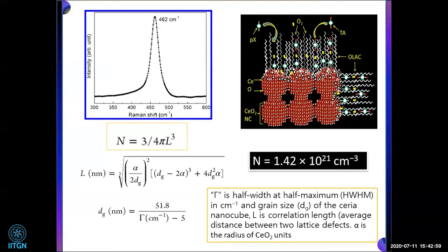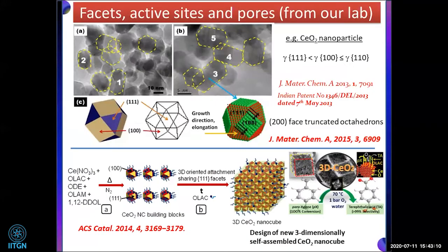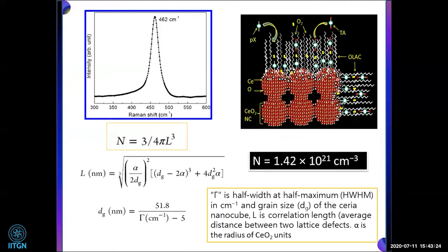So what is that? It is actually when we prepare the nanocrystal, it is engineering, right? We are doing crystal engineering. With the help of this, as I said, using surface selective solvents or surfactants, we can make the nanoparticle with special, exposed facets. So we made that, and we got only 100 facets, and that gives a lot of oxygen vacancy. And you know why? Because the energy required to create the catalytically important oxygen vacancy defects, or oxygen storage capacity, OSC, is low for the low index surfaces, that is 100 and 110, as compared to 111.